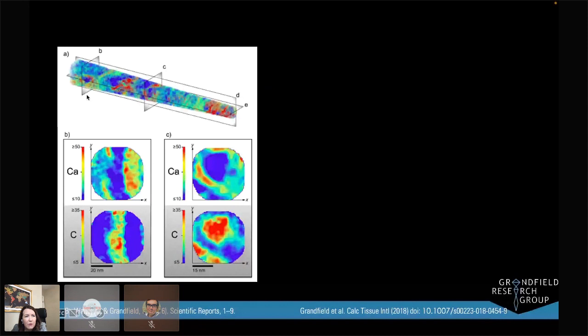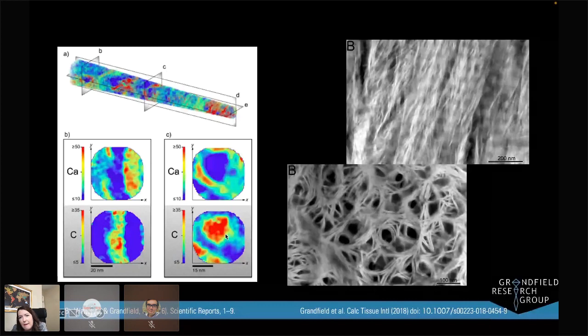We can explore this data down any direction in any portion of the data set. Here are two slices I'm showing, and what we see are some features where we have calcium-rich plates and carbon-rich gaps in between. In other areas, we see circular features with a collagen fibril in the center.